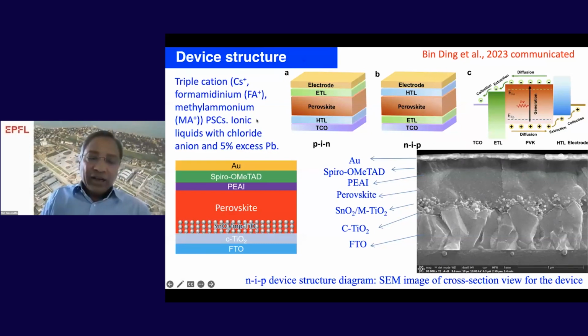In addition, there are ion migrations and defects. In order to decrease these defects and prevent the ion migration, we also use ionic liquids as an additive. In all these cases, at most 5% excess of lead will be used. There is a purpose for using this 5% excess lead iodide: you convert this excess into a two-dimensional perovskite, which we will see as we go into interface modifications. So this is the composition of the perovskite.